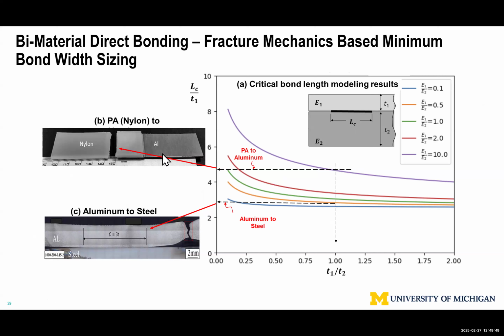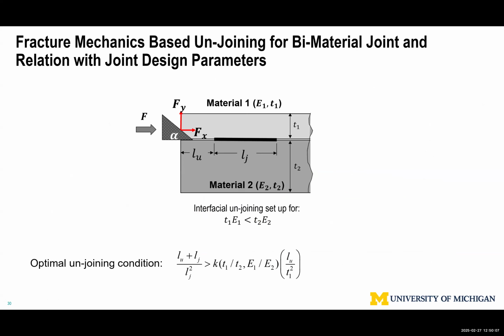For nylon to aluminum, the bonding width ratio is about 5. For aluminum to steel, based on the thickness ratio, it's about 3. We can demonstrate that this gives you the maximum strength. You don't want to overdo it, it's costly, adds material, and has environmental impact. You just want to do enough, right? So actually, to make it debondable, say anytime we want to open up something like a battery pack, this is important. It depends on the flexural rigidity ratio, and the alpha can be rotated to this side, and that provides the maximum driving force to open up a crack.